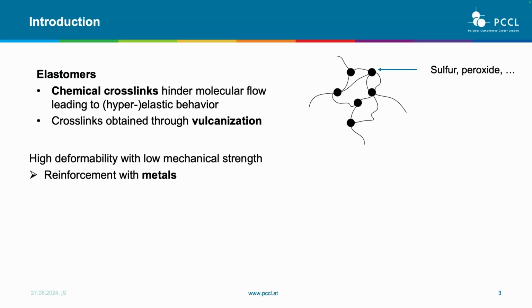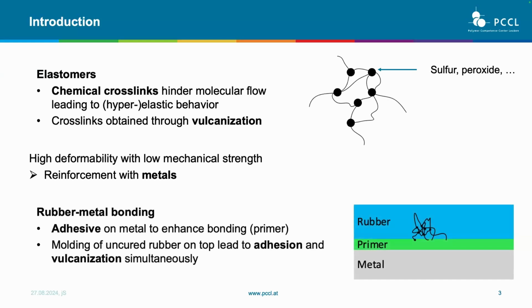Generally, in structural applications, these materials are often coupled with metals, and therefore, how is the coupling performed? Normally, a primer is applied on the metal surface, and then the rubber is vulcanized directly on top of the metal in a mold and heated up to the vulcanization temperature. Then we have the creation of the vulcanized rubber and this complex interface that allows the adhesion between the rubber and the metal itself.